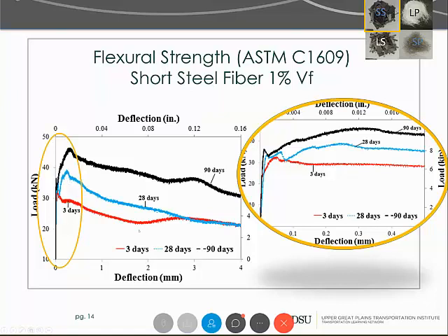And those might be a little better because they actually characterize the entire toughness into that number instead of just a single value. But that aside, there is obviously a different value that you're going to get with age. Because the peak load is increasing a little bit here between the green and the black, the residual strength ratio, because you're taking this stress value at 3 and then dividing by this value, because both of them are increasing, you tend to get maybe not as much of a benefit, or it seems a little more consistent, but these don't increase by the same magnitudes. So that's what we look at later when we look at some more properties here.